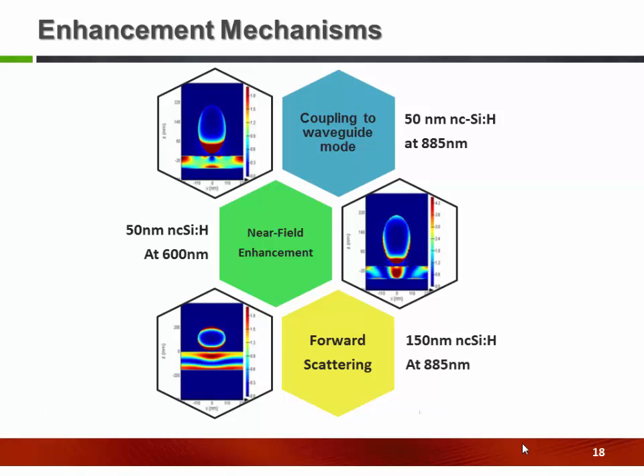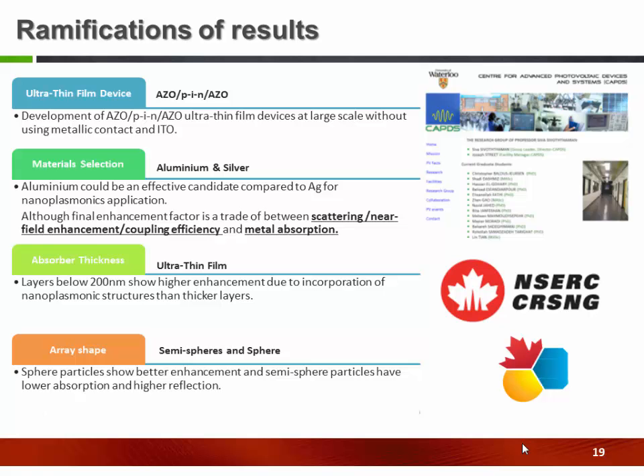The problem is that all of these mechanisms are involved in improving the performance, and if some parameters change, they play different roles. Sometimes, for example, forward scattering is really important for a nanoparticle array. And if we change the position of the nanoparticle array from the top side to the back, we lose this forward scattering performance. Although we still have, for example, near field enhancement or the coupling mode, we are not going to see any improvement from the forward scattering. But at the same time, we could see some minor performance improvement as well.